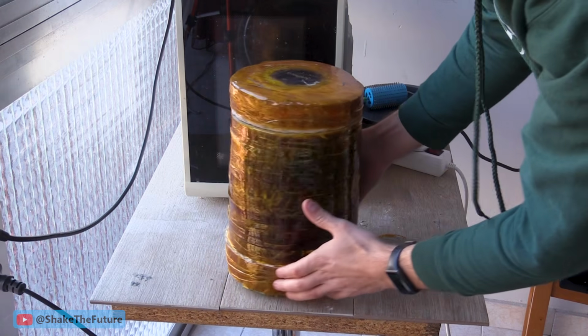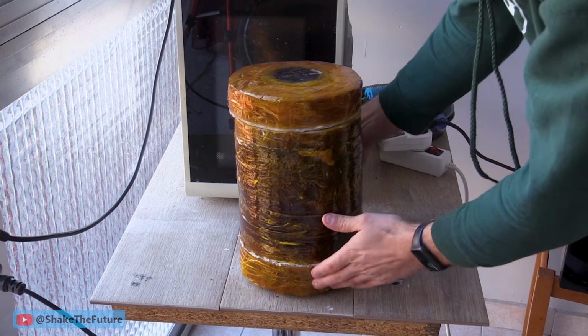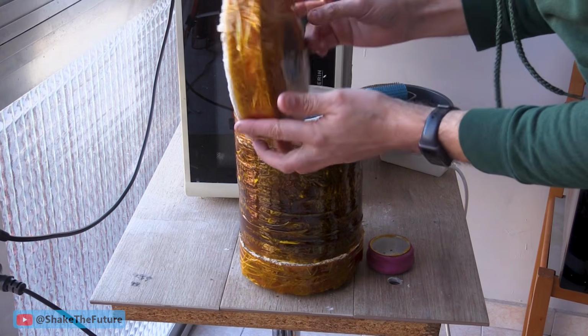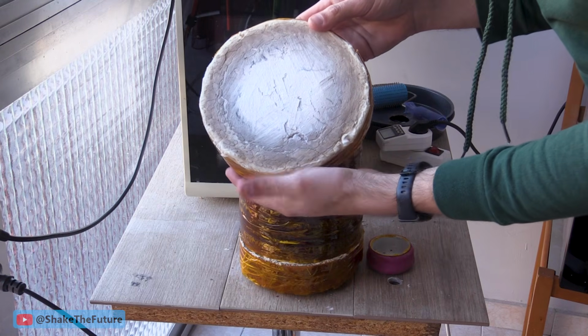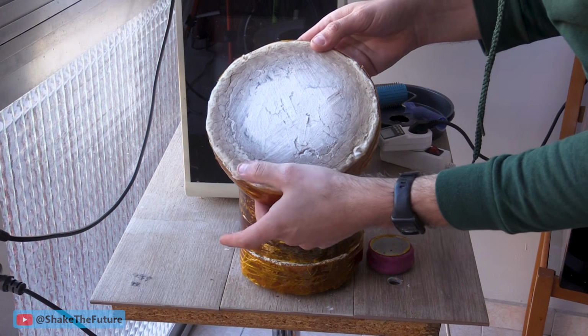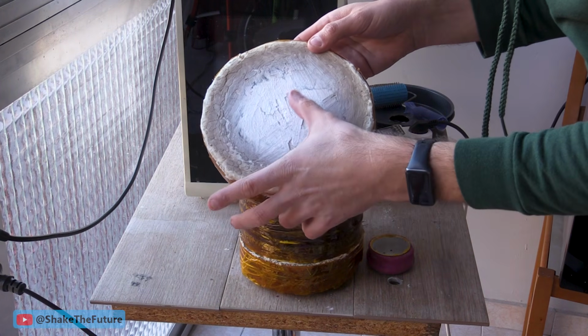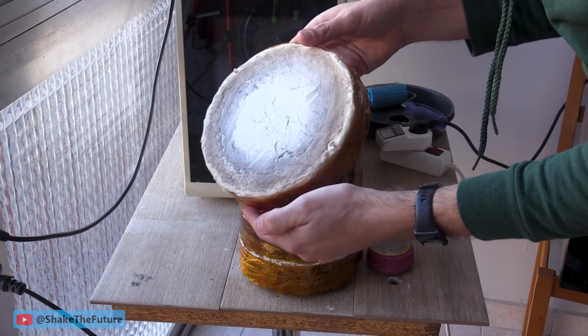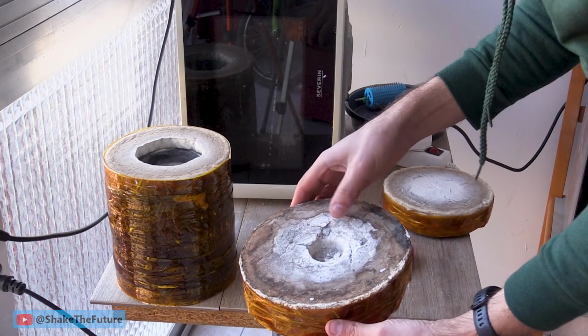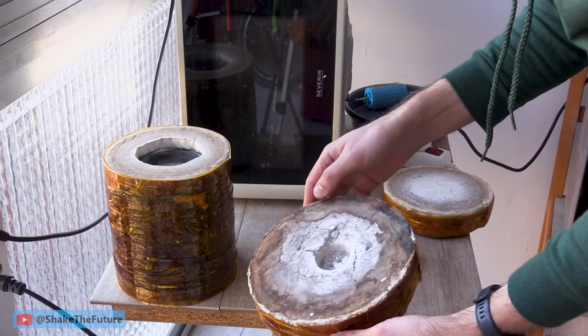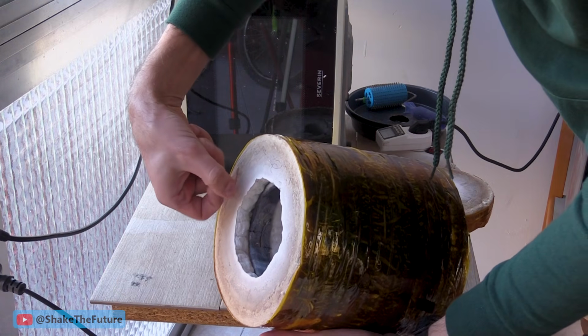So here's the same kiln you just saw me make after 3 years of use. The Kapton tape has become dark. I actually believe it could be the adhesive that has darkened, but I'm not 100% sure. I delayed the maintenance of the kiln because I knew I wanted to show it on the camera. In fact, I might have let it go a bit too much.